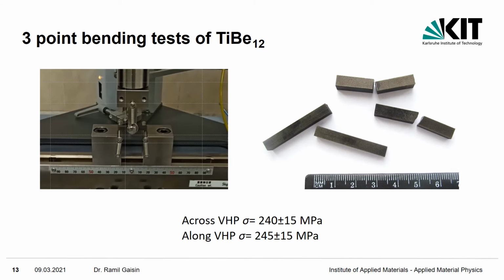Titanium beryllide is considered a functional material for fusion reactors. Therefore, it does not have strict requirements for mechanical properties. However, this is of interest to the aerospace industry. 3-point bending tests were performed at room temperature. They did not show any significant difference between the two directions of testing, across or along vacuum hot pressing. The flexural strength is about 240 megapascal, and this is typical for beryllides.